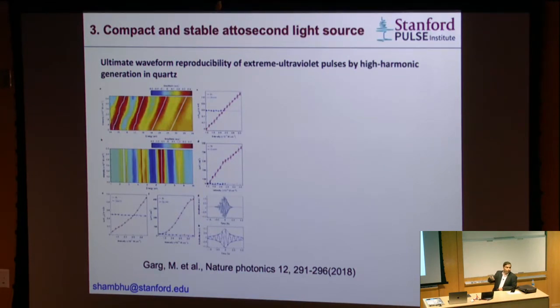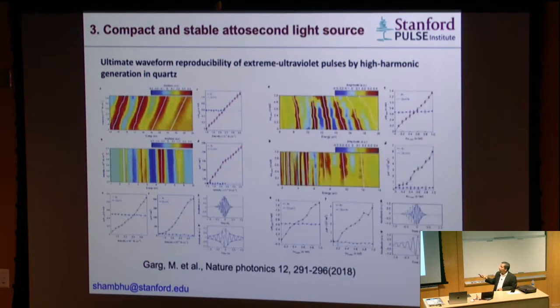Why? Because lasers typically fluctuate, right? When the laser fluctuates, the photon energy of the harmonic could also move. You want to know what type of dependence you have. So the top is the gas phase. There is certainly a significant change of the photon energy as a function of laser intensity. This is the solid quartz, which is much more sturdy, as you can see. Similarly, there is also dependence on what's called the carrier envelope phase, which becomes important for really short pulses, like single cycle or 2 cycle pulses. And they observe the same thing. In the gas phase, there is lots of deviation, and in the solid, things are much more stable.